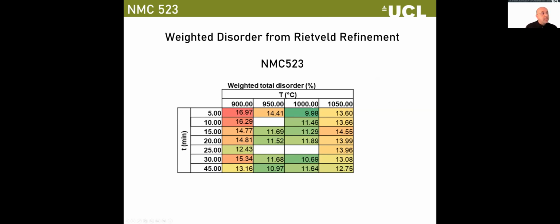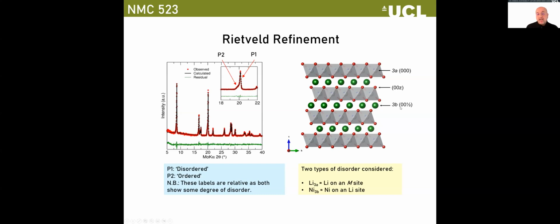And by the way, most people believe that when you make an NMC cathode, you're going to heat treat for 8 or 12 hours, and after that time, you're going to get a total amount of weighted disorder of below 5%, typically 2%. And that generally means that you've got this wonderful idealized structure where the lithium is all in between there, and that you've got very little lithium on the nickel side, or nickel on the lithium side. I should say that's because they're of similar size. I think it was nickel 3+, which is a similar size to lithium plus.